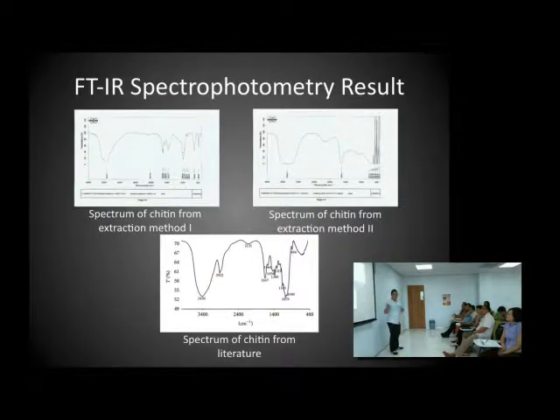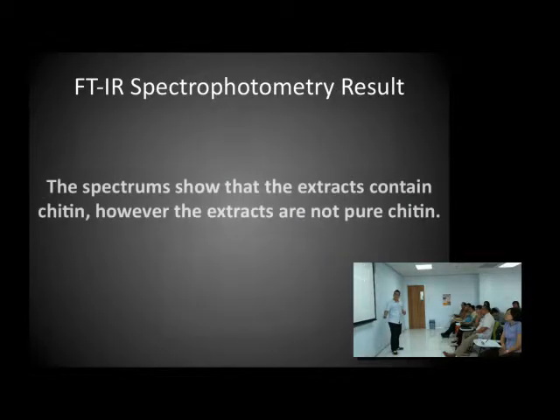Here is the IR spectrophotometry result. If we compare both spectra of the extract with the one from the literature, well, we can see that it's not exactly the same, but it has similarities. Therefore, it can be concluded that the extract contains chitin, but the extracts are not pure chitin.